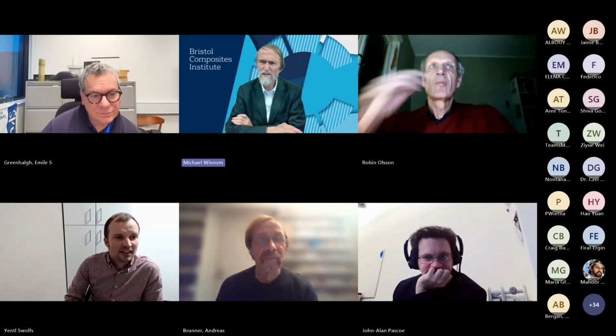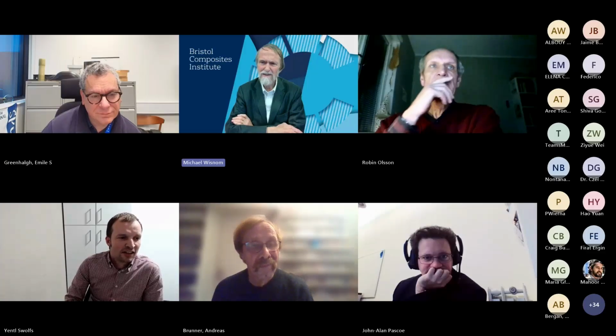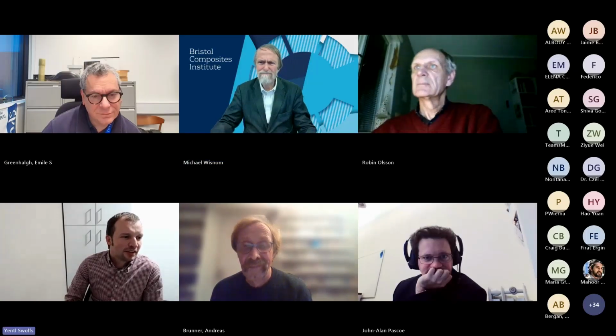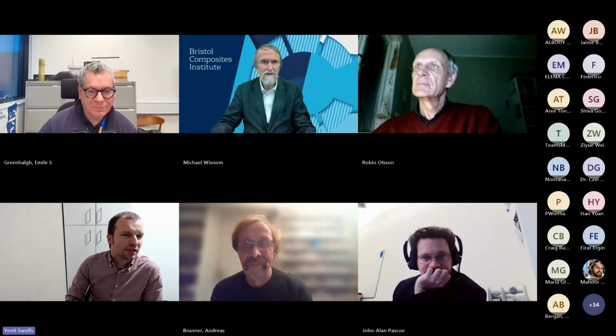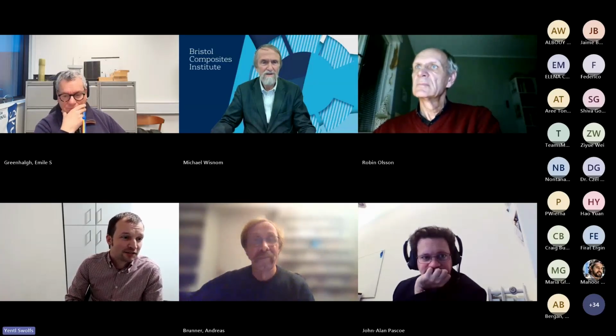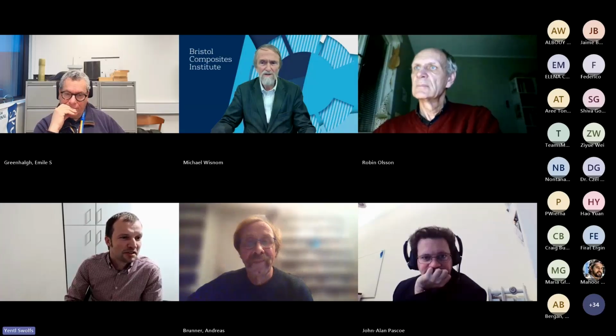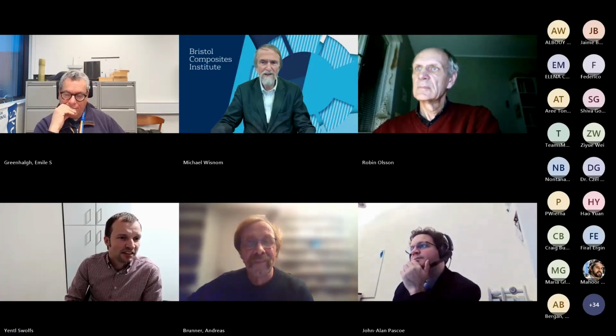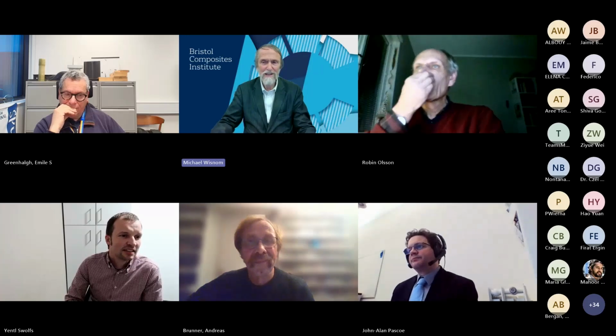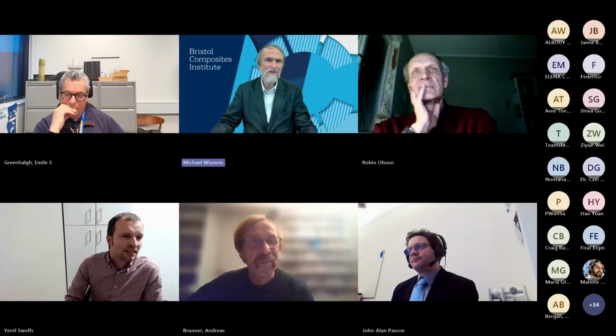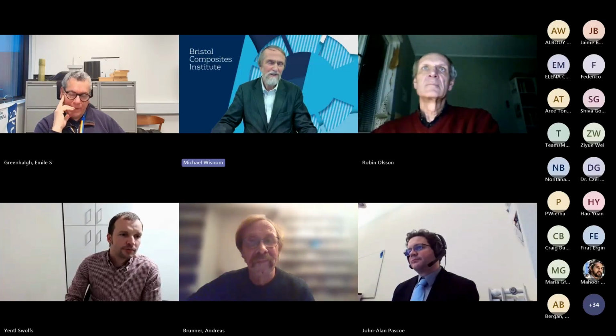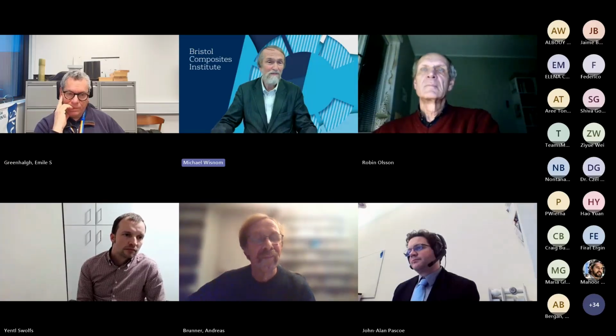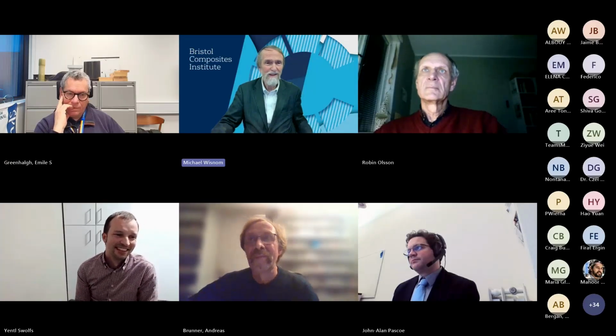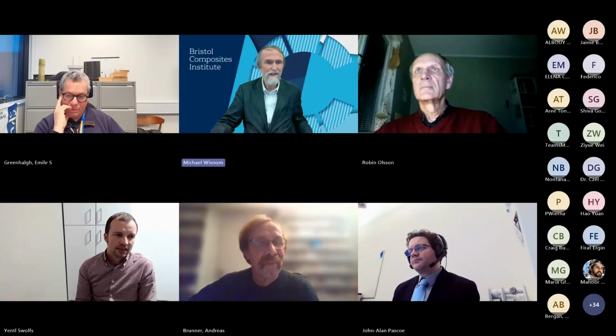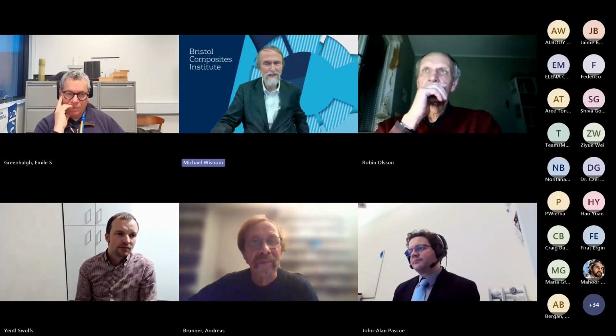Right. Okay. These values for size effects. So I'm not quite sure what. But I guess if you test a much wider specimen, some of these type of tests have been done for sure in setting up the standards. I guess also including for mixed mode bending, although I don't know specifically whether that happened. One of the things depends how you define size effects. I think size effects in my book are more associated with strength rather than fracture. But I think a crucial one is the effect of specimen thickness, because especially in mode 1, maybe we were supposed to be talking about mode 3 and other ones, but in mode 1, fiber bridging is really strongly dependent on the stiffness, which depends on the thickness of the specimen.